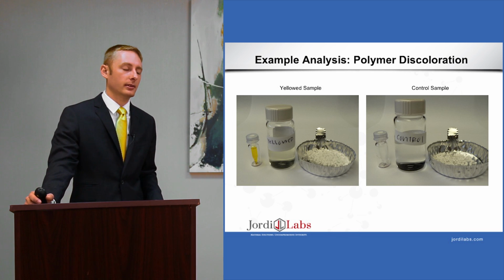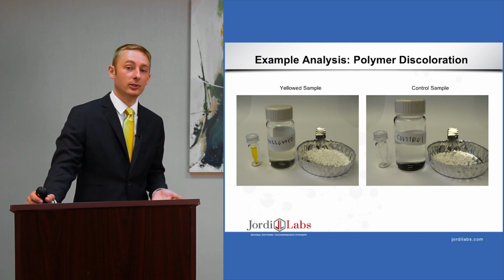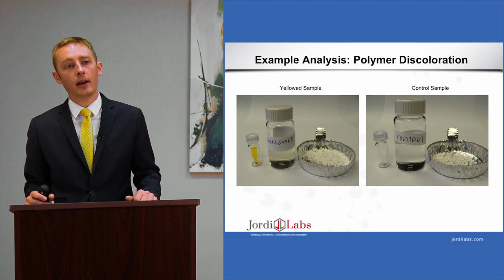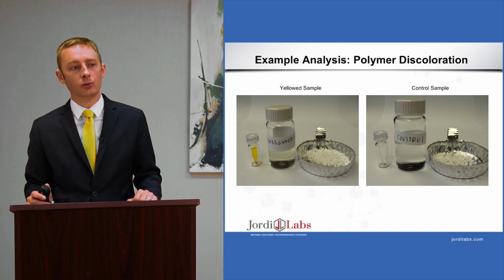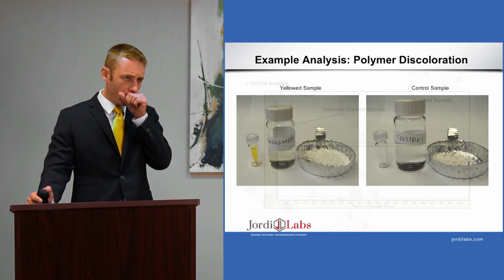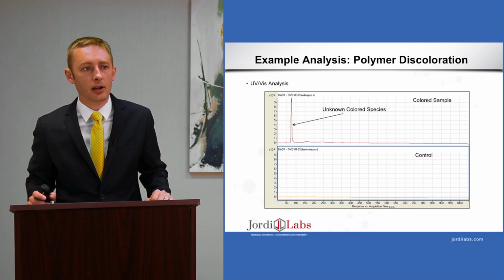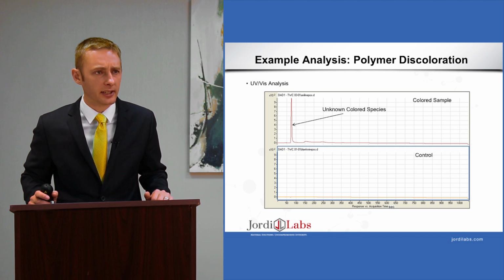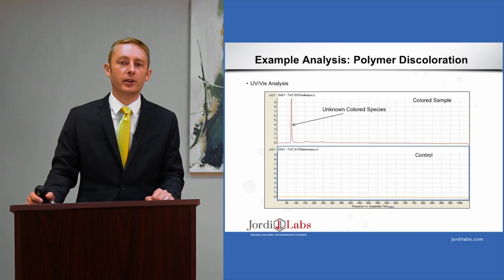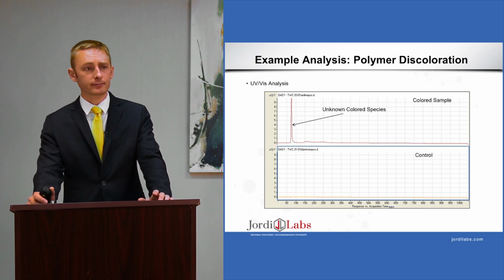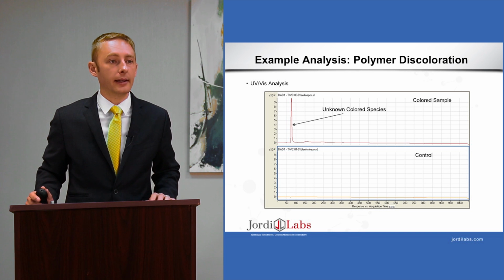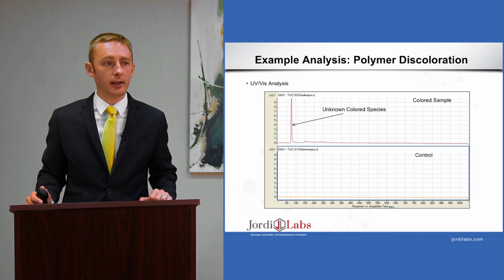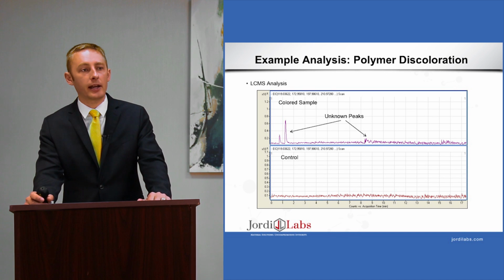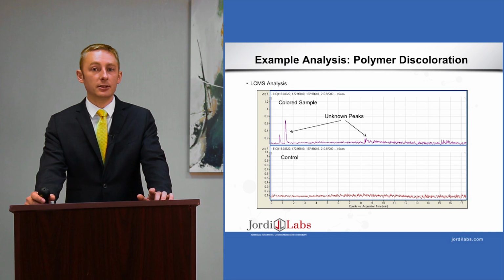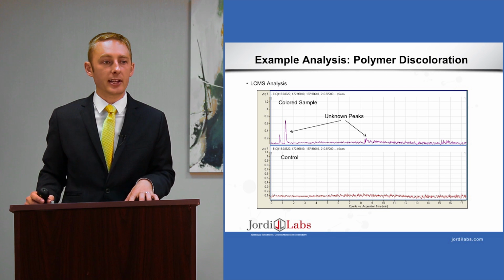If it was uncolored, we might start by doing elemental analysis on the polymer sample neat, because a pigment wouldn't normally dissolve in an organic solvent. After injecting this on one of our LC-MSs, this one was equipped with a UV-vis, and I believe it also has a CAD detector as well. We see an unknown colored species that comes out quite early in our colored sample, but we don't see it in our control. In the next slide we're able to identify several EIC peaks that are present, that are coming out at that same time.